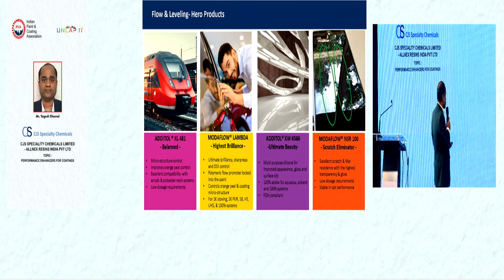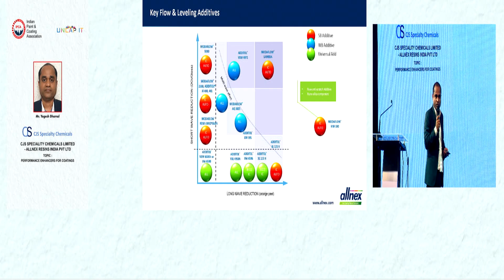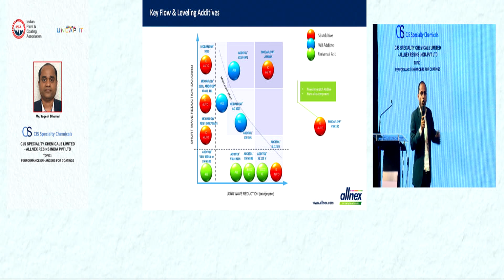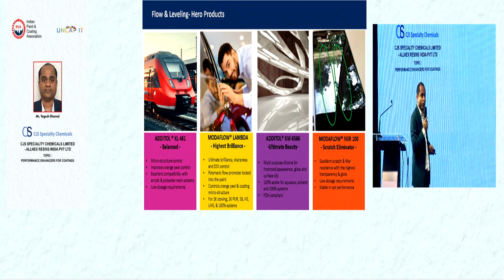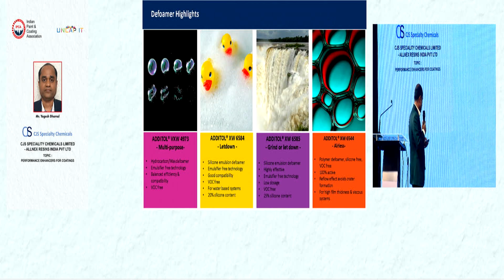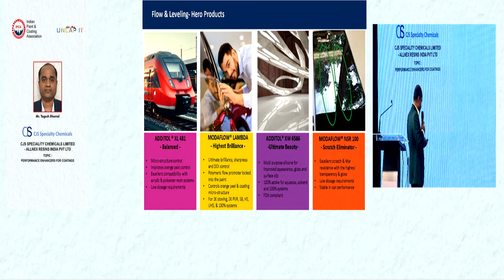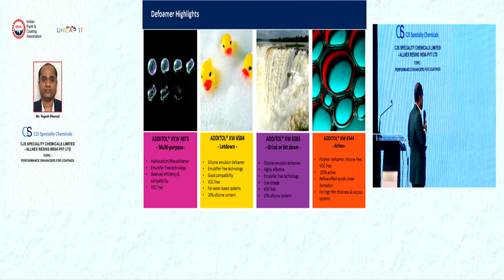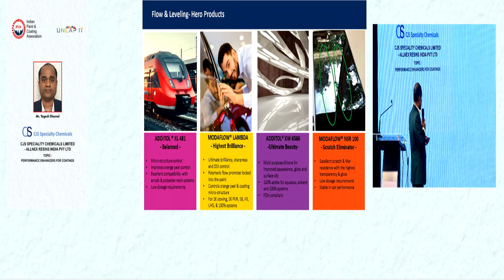From the product portfolio side, we again have various chemistries. We have categorized those based on their molecular weight and on the compatibility in different solvents. So it's a very wide range. If you need any details, you can contact us at any time. Just the hero products from the flow and leveling category. Again, XL481 is a microstructure control additive. It is a cost-effective acrylic flow modifier, I would say. It has excellent compatibility with acrylic and polyester resin systems. It requires a very low dosage.